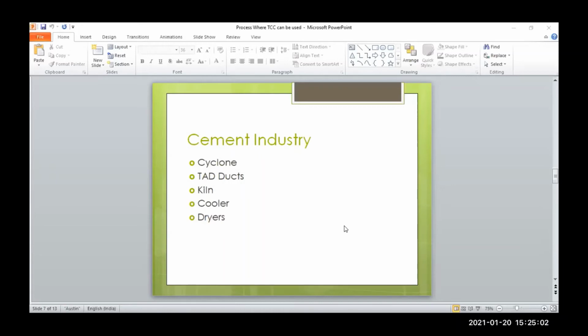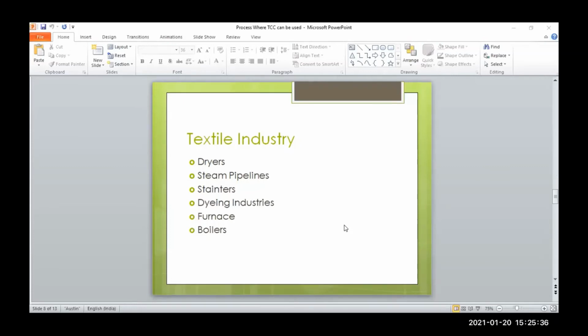Then the kiln is there, where the shell temperature varies from 250 to 550 degrees centigrade. We can also apply that coating on the external shell there. Then there are coolers, dryers, and various heating equipments in the cement industry. Also, there is the textile industry where dryers are there, steam pipelines are there, stenters are there where fabric is straightened. Then there are dyeing industries, furnaces, boilers, all can be applied with this coating.